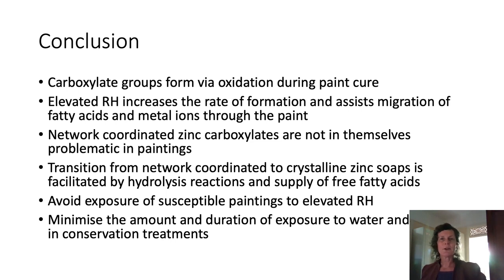Network-coordinated zinc carboxylates are not in themselves problematic in paintings. However, hydrolysis reactions or supply of free fatty acids from additives or other layers within a painting will encourage zinc soaps to crystallize. Prolonged exposure to elevated relative humidity is best avoided. And while the potential impacts of specific treatments on susceptible paintings remains an active area of research, risks can likely be reduced by minimizing the amount and duration of water and solvent applied during treatments.